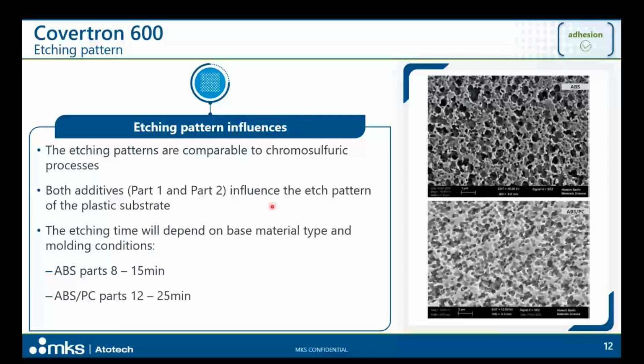And as mentioned before, the etching time will depend on the base material, the resin. The molding conditions also play an important role, like currently with the sulfuric-chromic etching. We can say that the regular etching times with the Covertron 600 for ABS normally move between 8 to 15 minutes, and for ABS-PC parts, we move from 12 to 25 minutes when we have special materials.